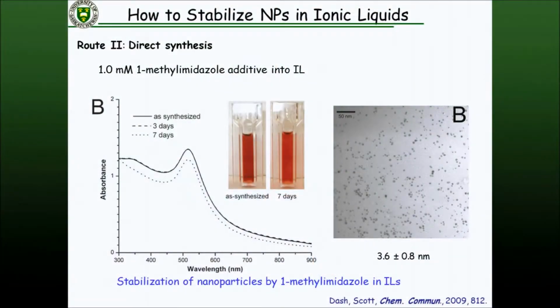And at the levels we're making particles, in the micromole concentrations, even at millimole levels of methylimidazole, you're still talking about 30 to 40 methylimidazole molecules per nanoparticle that are available in that ionic liquid. So even at low levels of impurity, there's still a substantial amount of impurity to stabilize nanoparticle surfaces.